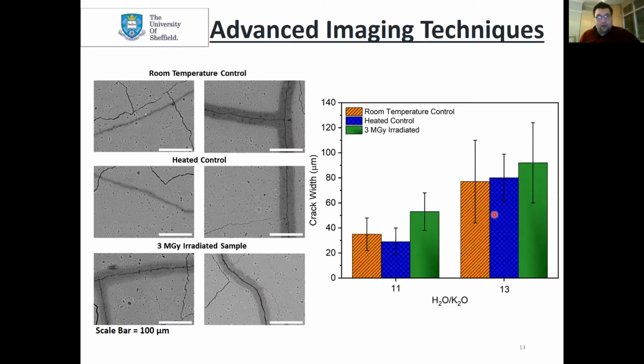The crack widths go up slightly with irradiation, but they're well within the error, so there isn't a massive amount of cracking in these samples based on irradiation. This shows a really stable system has been formed.